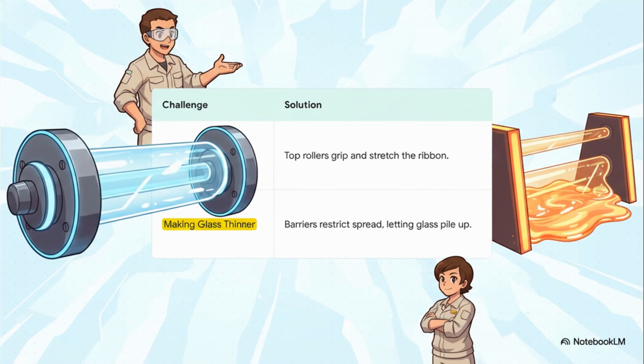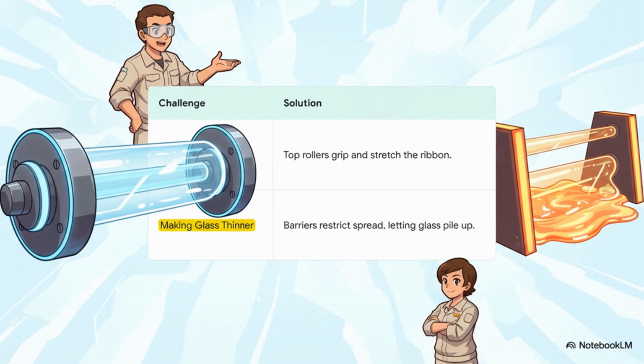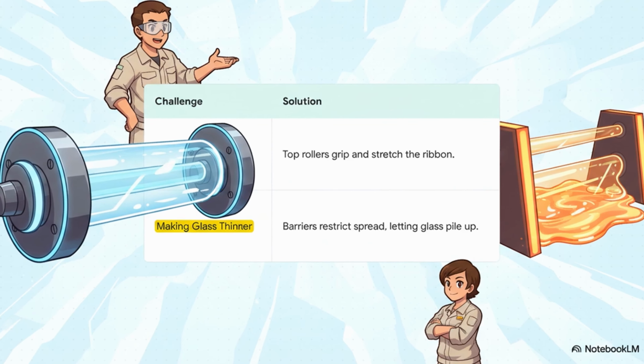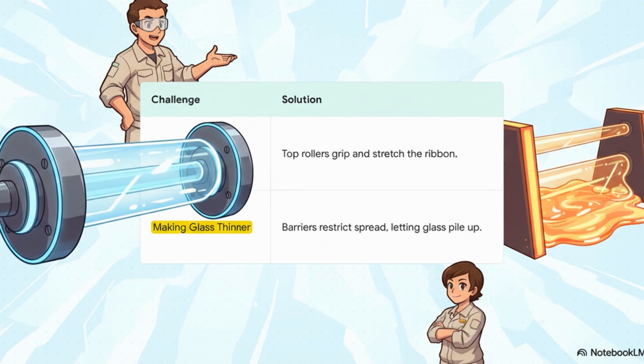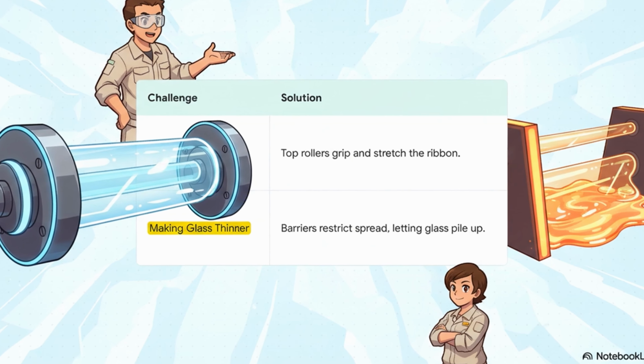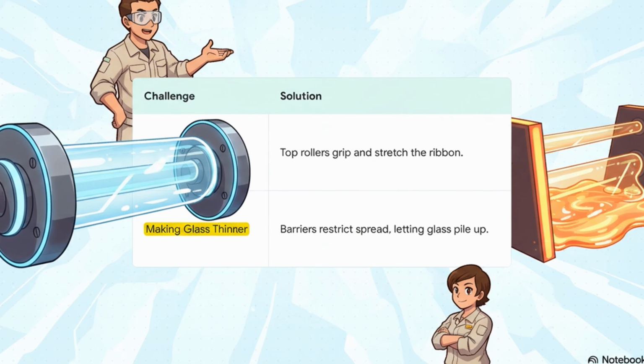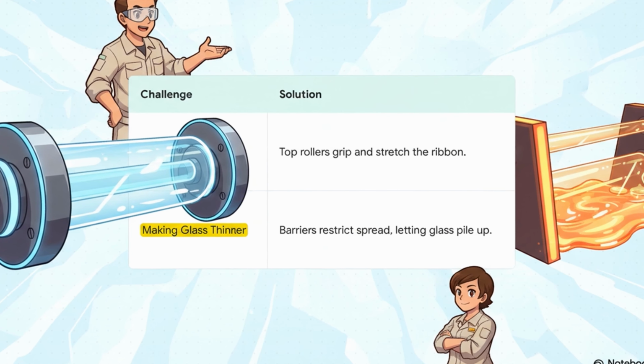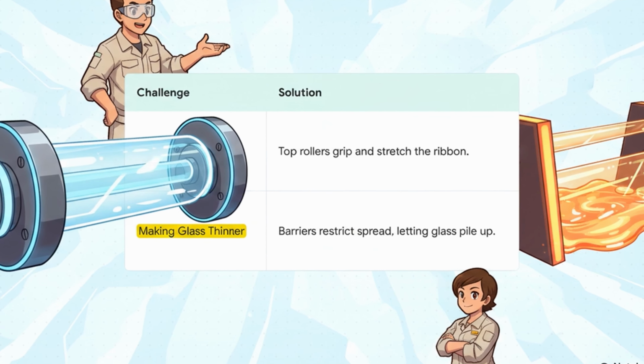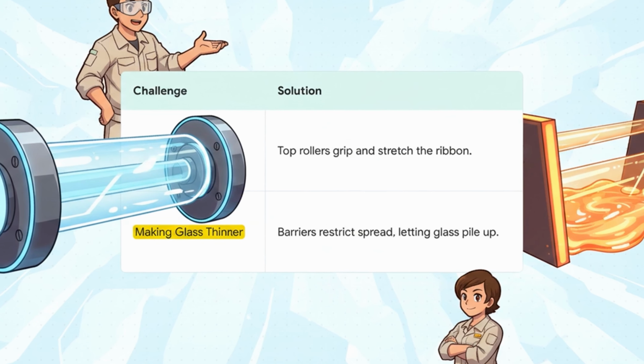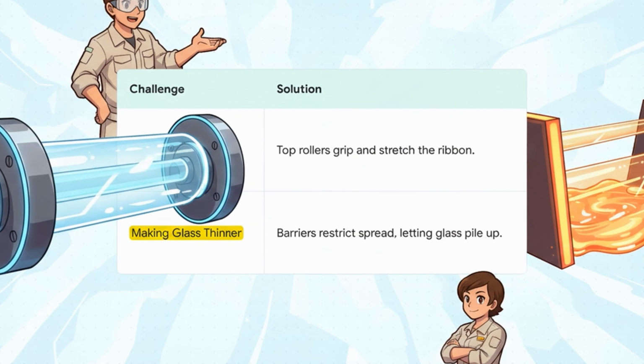And this is where the engineers got really, really clever. To make the glass thinner, they use special top rollers that gently grip the edges of the glass ribbon and stretch it out while it's still soft. And to make it thicker, they put in special barriers that don't stick to the glass, restricting its spread and basically letting it pile up on itself before it hardens.